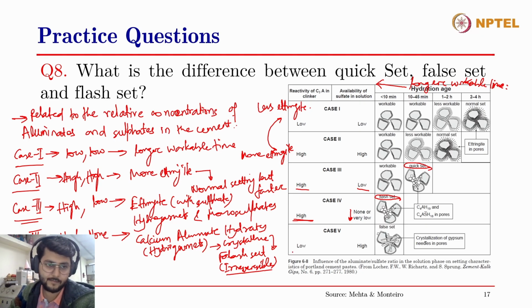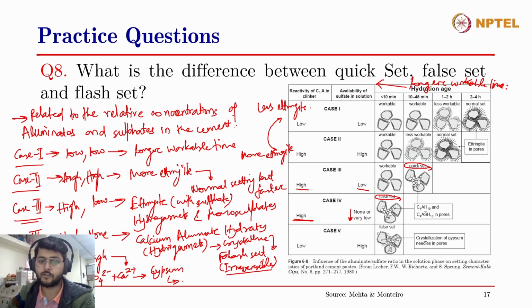And the final case is that of a false set. What happens in false set? When the C3A content is low but there is enough sulfate available, so there is too high an amount of sulfate available in the system, what happens is these sulfates combine with the calcium coming from the different clinker phases and precipitate gypsum, and this gypsum leads to a false set.